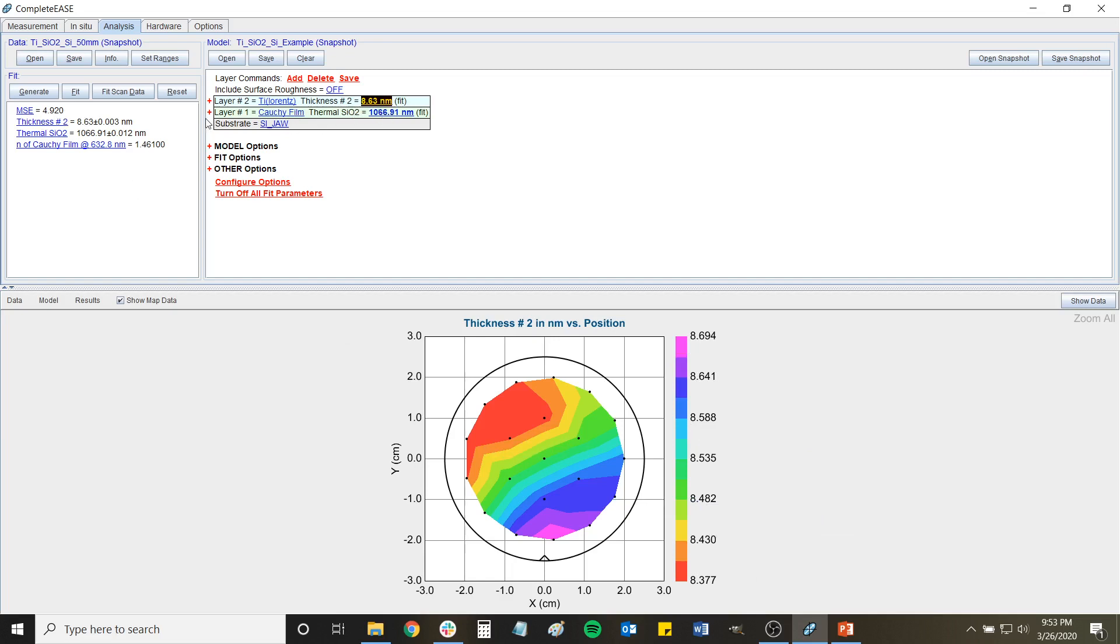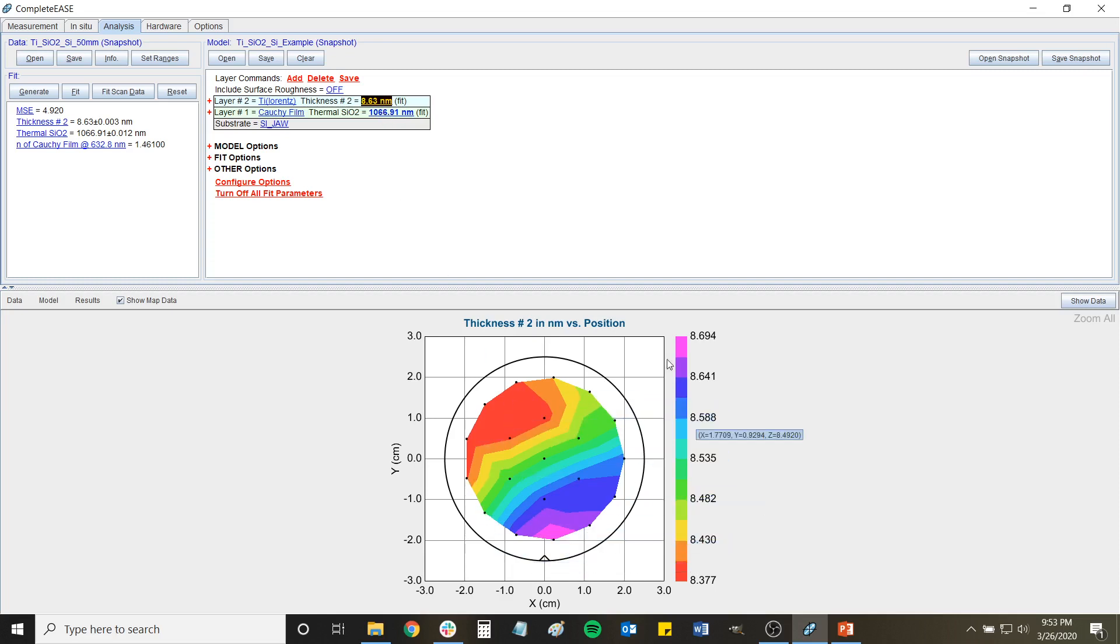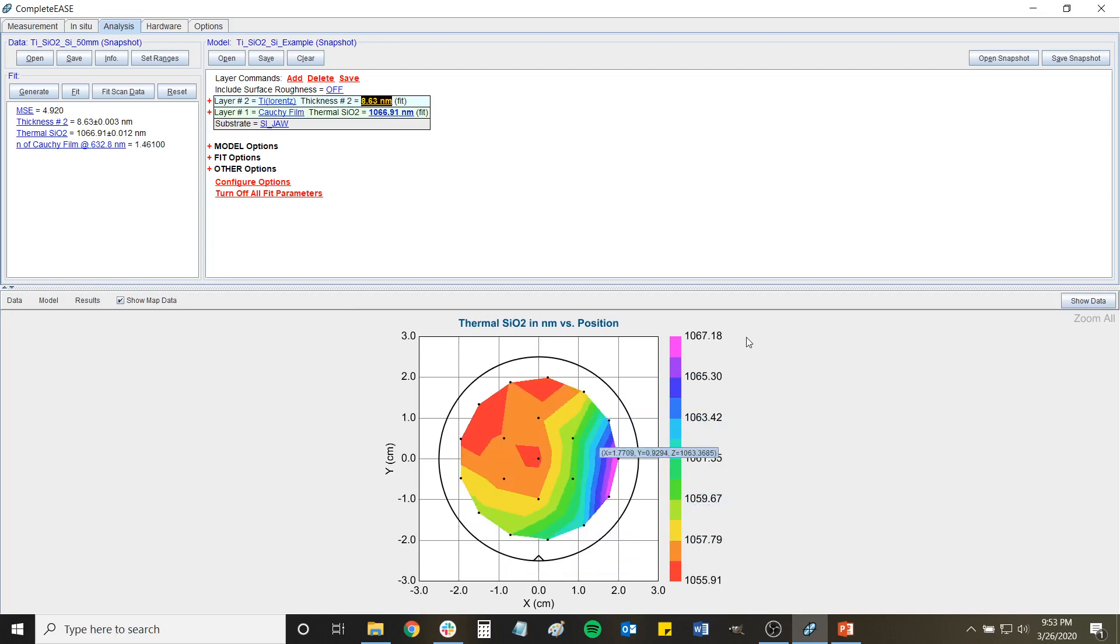Now you may notice, okay, I am fitting the thickness of this thermal SiO2, and you might think, well couldn't that throw that off? It can, which is exactly why I'm fitting it. I do know that this is accurate because I've done this in kind of stages, and this is how I'd recommend you do this.